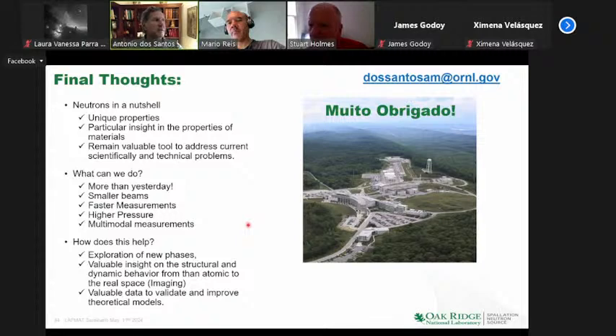There is a development, I think it is published, where we put a ruby on a clamp cell, but not all instruments can have it measuring in situ when it's cold. So basically you just measure it when you change pressure anyways. And in the clamp cells, we do add an internal standard, which is basically lead powder or sodium chloride powder with the sample. And then we just try to go from an internal standard if we can.